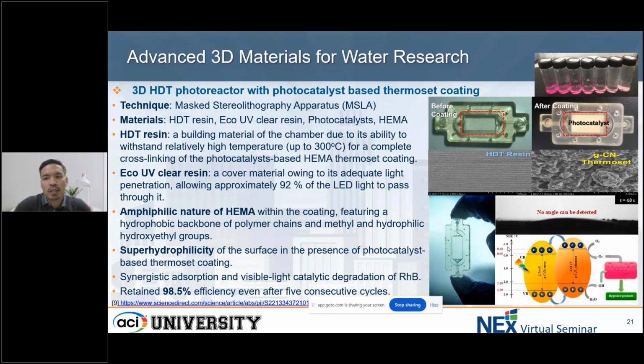And why do we want to coat the photocatalyst, and why not just use the photocatalyst itself? Because the photocatalyst is in powder form. When you have a powder form, you need an extra post-processing step, which is centrifugation, and it gives more energy consumption. So we are trying to avoid centrifugation, and this photocatalyst coating is well coated on the photoreactor itself, and it will avoid the leaching and avoid the centrifugation. It really helps a lot with time effectiveness.